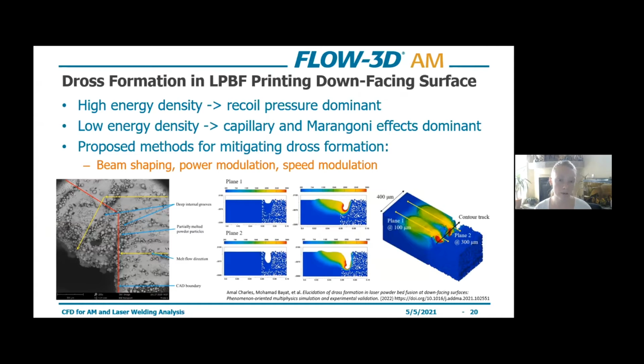What they have proven through numerical models is that with high energy density, so think higher power, lower speed, you're going to have recoil pressure dominant forces, and that'll lead to more keyholing. While when we have lower energy density, so lower power, higher speed, excuse me, capillary and Marangoni effects will be more dominant in that scenario. So that's kind of what we're trying to gain. You have better process control when you're operating in the sort of Marangoni dominant realm for the most part.